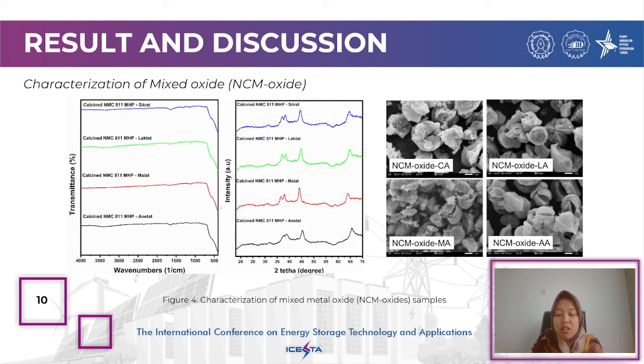Figure 4c presents the same analysis of the NCM oxide particles. Overall, all the samples are similar in size and do not form severe agglomeration. However, unique morphology can be seen in NCM oxide from acetic acid and lactic acid, which have quasi-spherical-like morphology with opening. NCM oxide from malic acid and citric acid has similar quasi-spherical particles covered by submicron primary particle adherence.